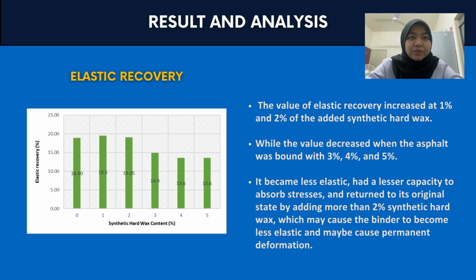Elastic recovery is used to evaluate the recovery ability of asphalt binder after elastic deformation. From the graph, the value increased at 1% and 2% of added synthetic hard wax, while the value decreased when the asphalt was blended with 3%, 4%, and 5%. It became less elastic, had a lesser capacity to absorb stresses, and returned less to its original state when more than 2% synthetic hard wax was added.